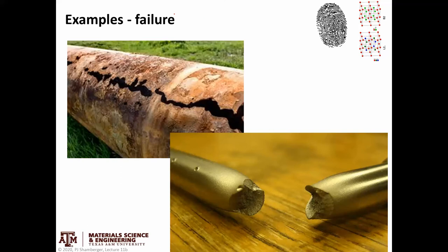Another example is a failure problem. Say you make the world's greatest alloy, use it, and then it fails — maybe it fractures or corrodes — and you want to know why. Sometimes it's caused by an additional phase present in the system that you didn't expect. Maybe the material is interacting with the environment and having a chemical reaction, creating new materials. If you identify those components, you could potentially design ways to limit their creation in the future.